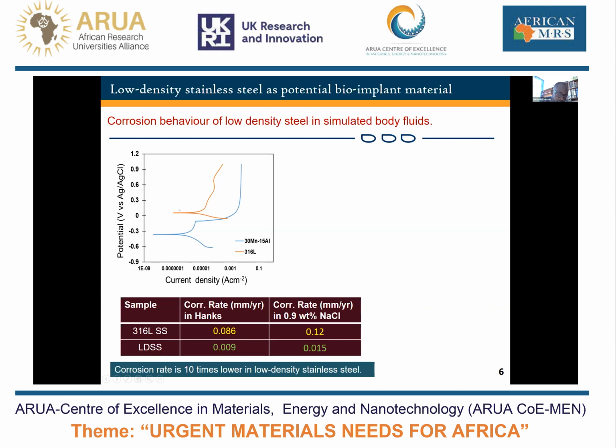Yes, from the curves you will see here that in terms of corrosion potential or Ecorr, the 316L is superior. But I learned from Prof. Sanderberg that what is most critical is the corrosion rate, because when corrosion starts happening, how fast is it happening? And that's what we want to focus on. So we thought that this is quite good. And considering that this is a commercial grade alloy and we were just testing the as cast sample, we thought that having this corrosion rate was quite beneficial. It's 10 times lower than that of 316L stainless steel.